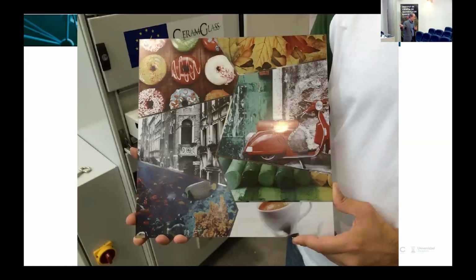And they are made by inkjet. So they're decorated by inkjet in raw, and then they go through the laser furnace and they come out like this. This is glass. This is glass which can only stand commercially, industrially in the process up to 680 degrees at most. The surface, this is at 580 degrees in volume. The surface is above 1,000. The glass is not damaged. You know, normal glass, this type of glass, which is float glass, can only withstand 60 degrees. And if 60 degrees, you put a heater to your glass window and it will break. We can put this to above 1,000 and nothing happens.